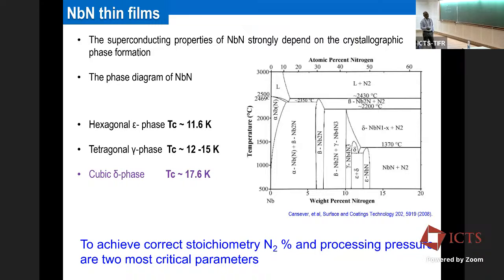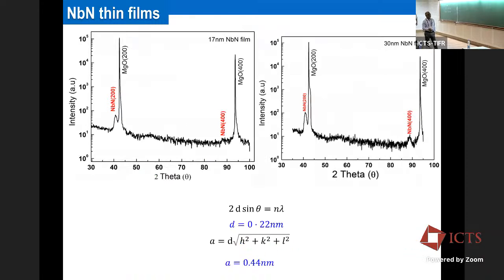And we have some other phases. If we deviate a little bit, with a slightly higher nitrogen pressure or a slightly varied chamber pressure, then other phases arise in the films, right? So we have to control these parameters. Different kinds of phases exist, and we are looking for the cubic delta phase, which has a Tc of around 17.6 Kelvin. To achieve the correct stoichiometry, nitrogen and processing pressure are the two most critical parameters.